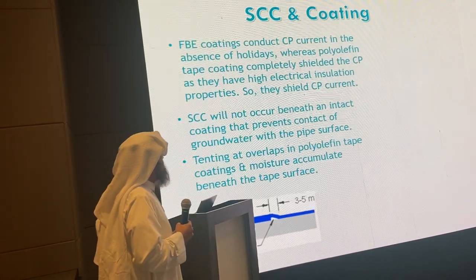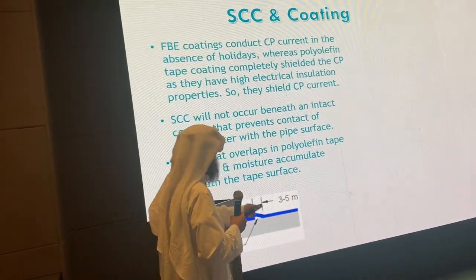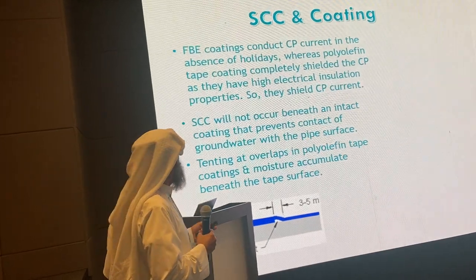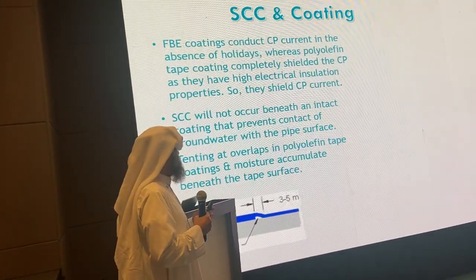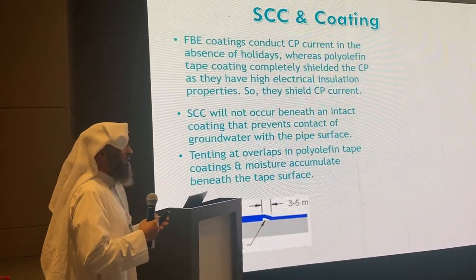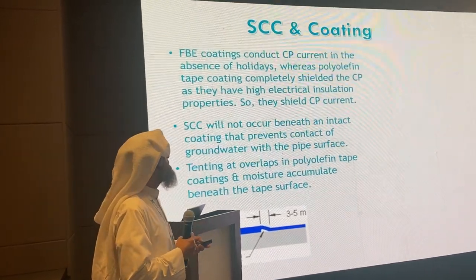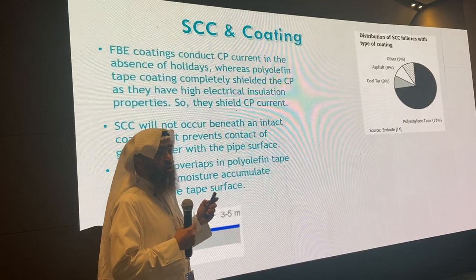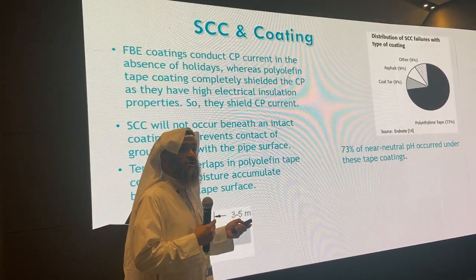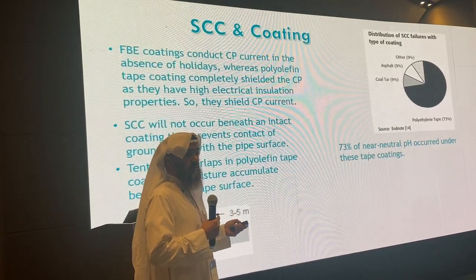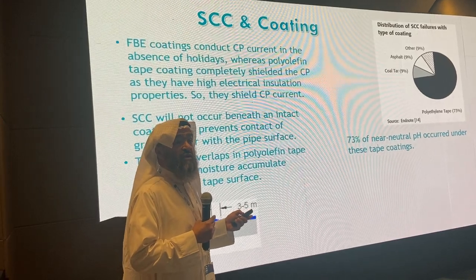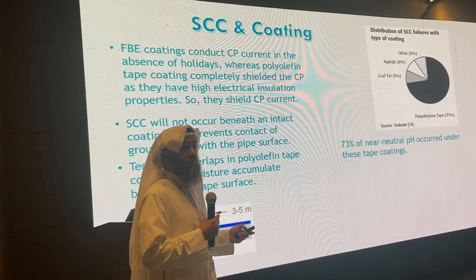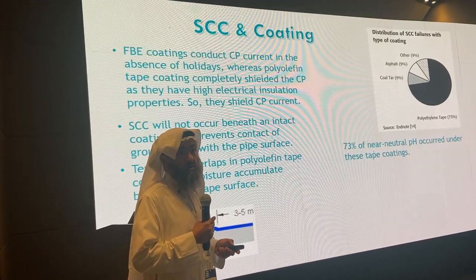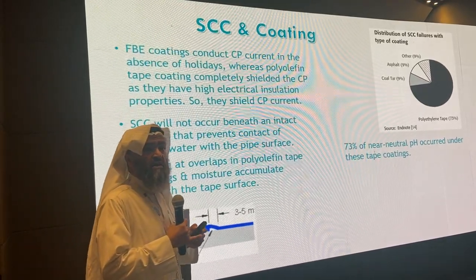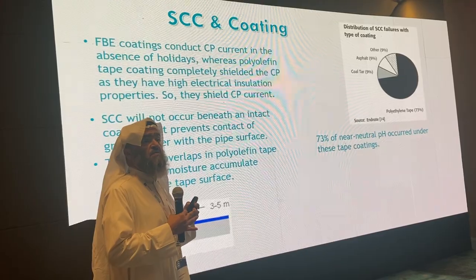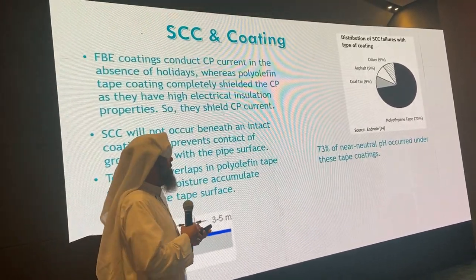So good adhesion will prevent shielding of CP. Then tenting at overlap in polyolefin, you can see in the picture where you have a tent because of the tape. These tents are locations where water accumulates, humidity increases, and electrical resistivity decreases also. 73% of near neutral stress corrosion cracking occurred with the polyolefin tapes. 2/3, 3/4 of the failures that we get are from using polyolefin tapes, including PE, PP, and PVC tapes, tapes that are outer wrapped by PVC, all are included in this.